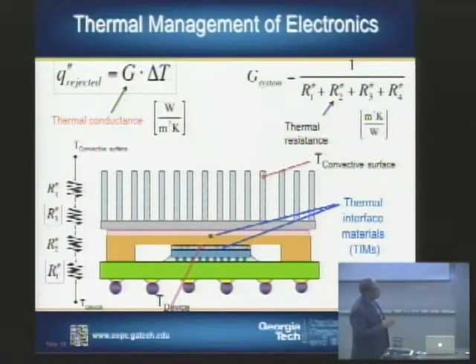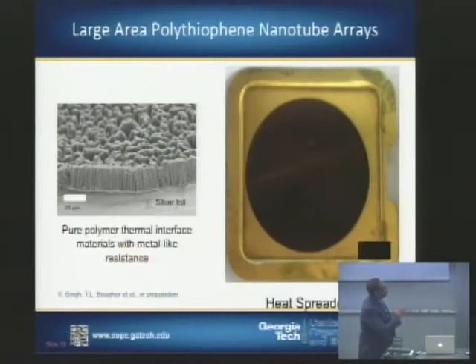But the major issue here is that if we have very, very large heat fluxes, we have to have very, very good materials in order to lower the contact resistance between the chip and the next layer. These are the issues that we're trying to address using thermal interface materials, by having very, very low interface resistances in areas where we have very, very large heat fluxes. And so in this work,